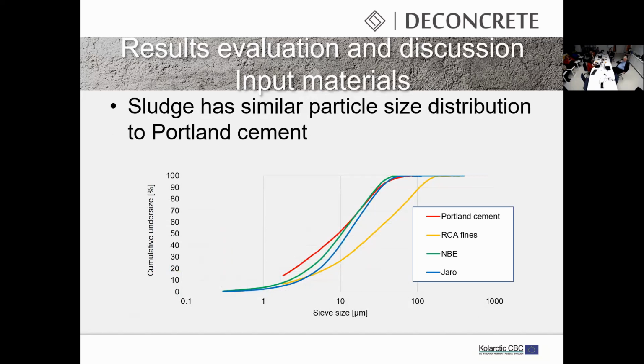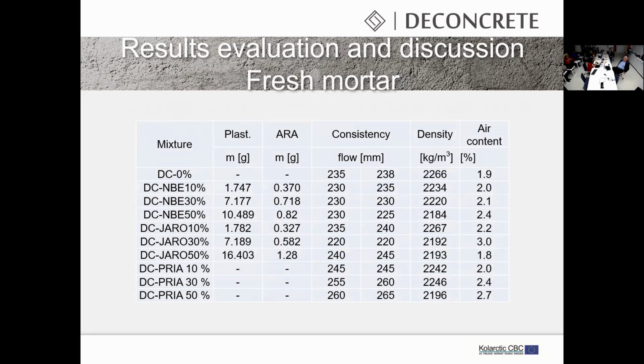Fineness of the materials: they were analyzed for particle size distribution, and for comparison, Portland cement is added in the figure. We can see that fines from production of concrete are much finer than the fines from crushing of concrete in the production of recycled aggregates, which was actually verified by the fresh properties of individual mixes, which we can see here.